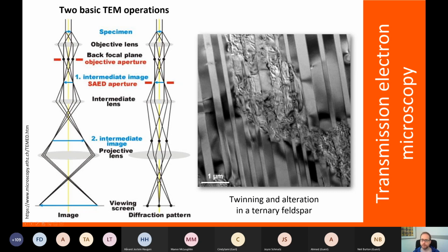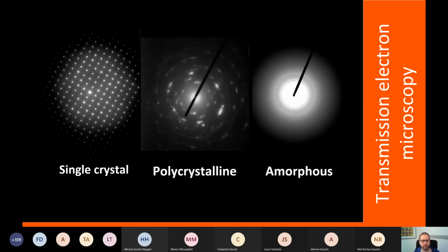But if we take the back focal plane behind the objective lens, we can also use this to get diffraction information. So images and diffraction are always happening at the same time in a TEM. It depends on what your TEM conditions are. Either you are in imaging mode or you're in diffraction mode. So you view the real image or you view the back focal plane of your material. And we will talk more about diffraction in a later lecture, as I said, but typically this is what these diffraction patterns look like. Some of you may have already seen this. This is a single crystal diffraction pattern here of, in this case, olivine, and the distances between these dots tell us something about lattice constants within our material.